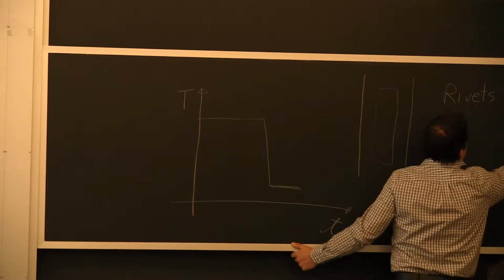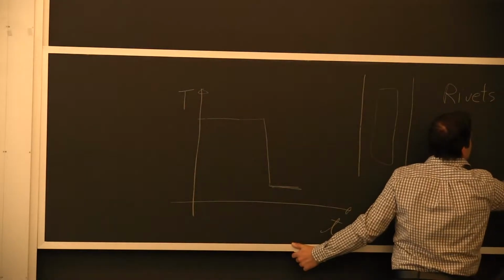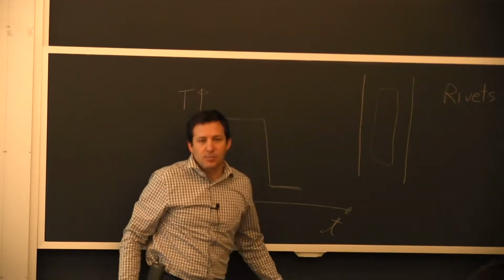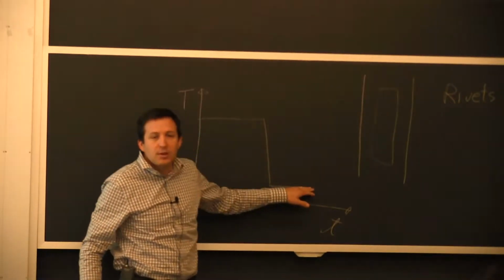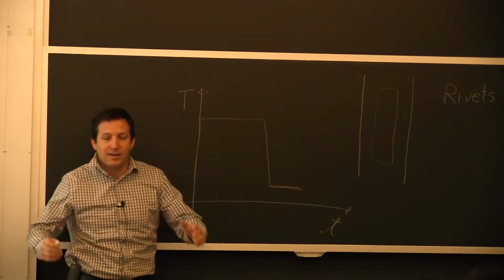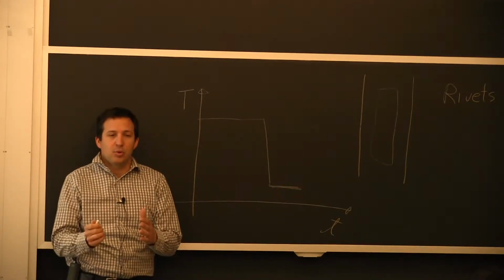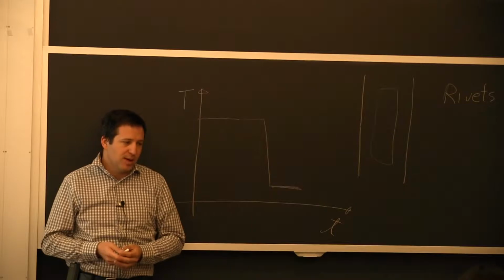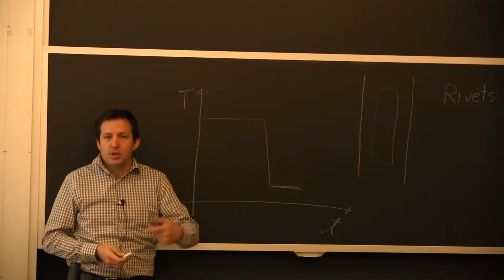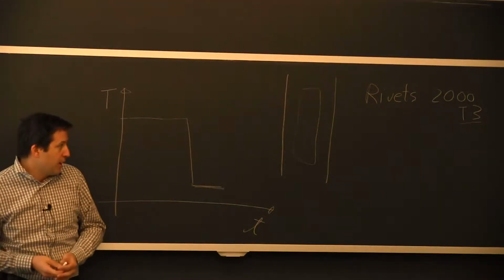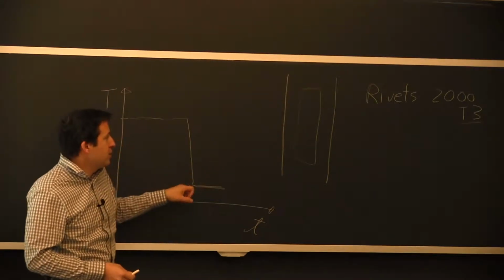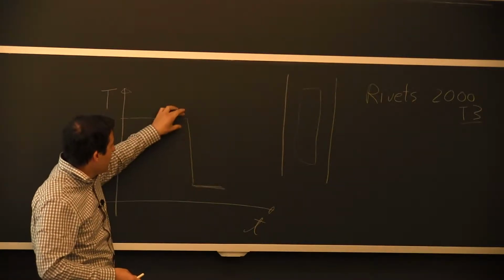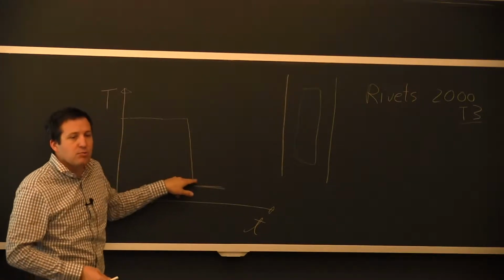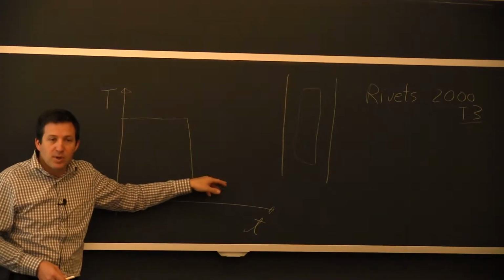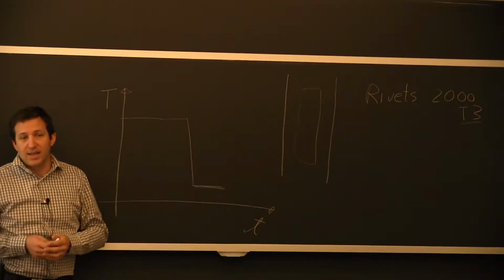There's a 2000 series, have a T3 temper, that's ambient temperature. It means that you don't have to heat it up after here, but you are forming precipitates. And the fact of deforming the rivet to make the joint activates the formation of these precipitates. It accelerates it, and it's also changing how they form. So it's a good combination of design to say, I'm going to quench it, it's going to remain relatively soft, then I do my forming, and over time it gains strength.